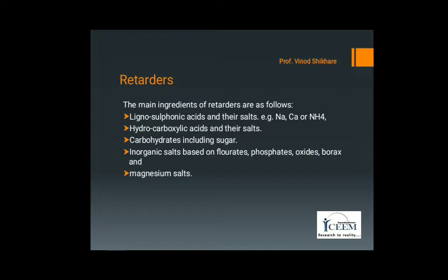One must be careful in selection of such ready-made retarding admixtures on account of heterogeneous nature and different molecular weight of retarders used with plasticizers. They tend to separate out. It happens when sugar solution is used as a cheap retarder. When retarders like gluconate are used, such separation or settlement of retarders does not happen.